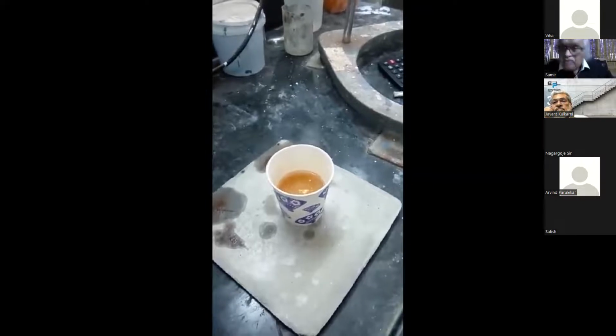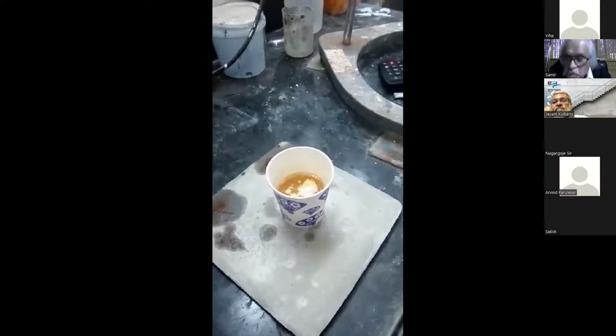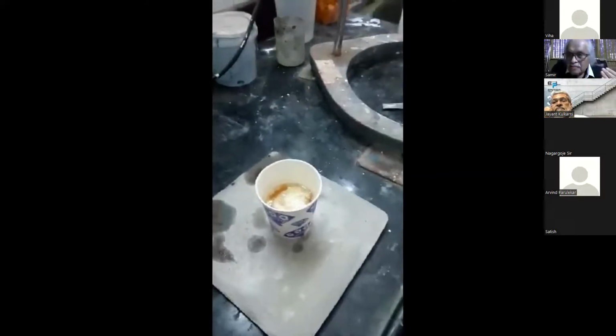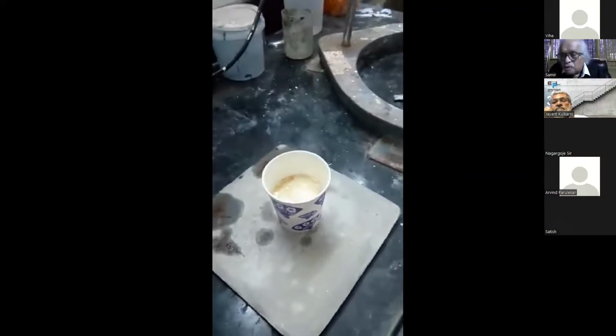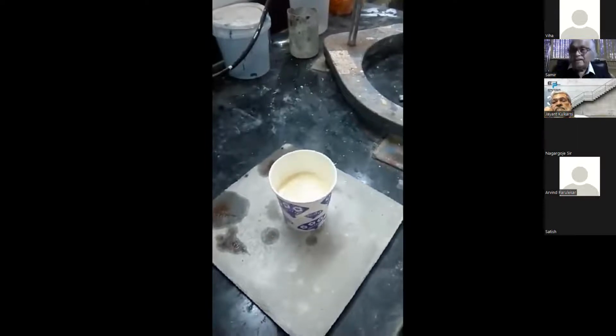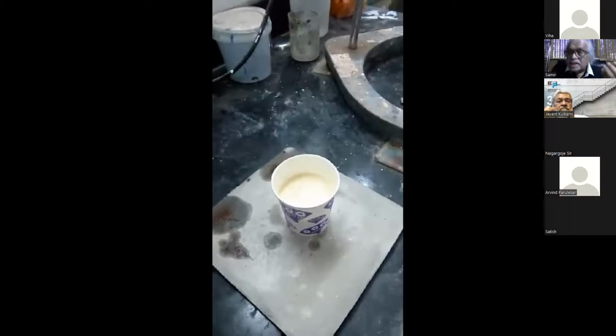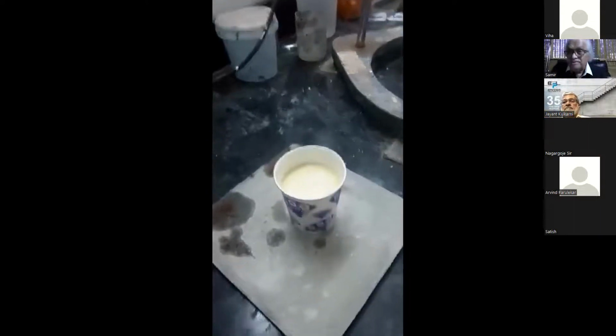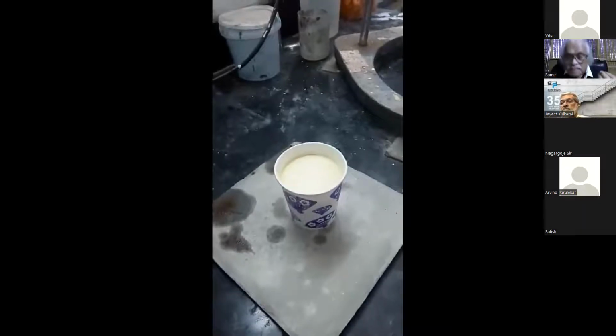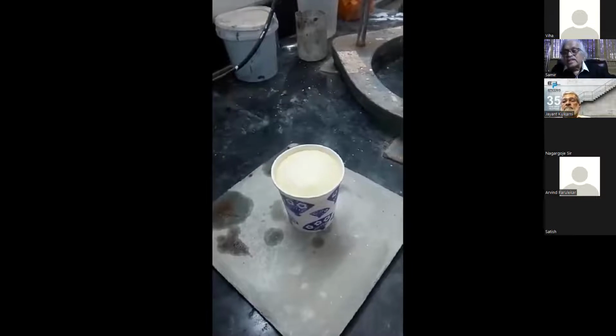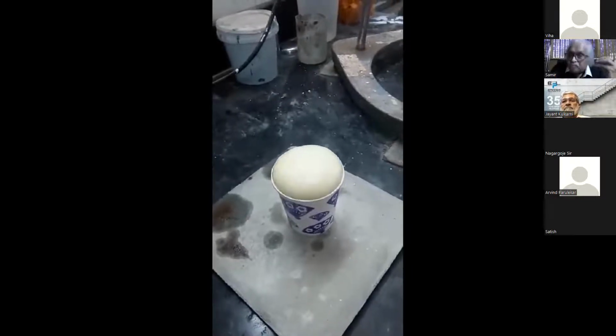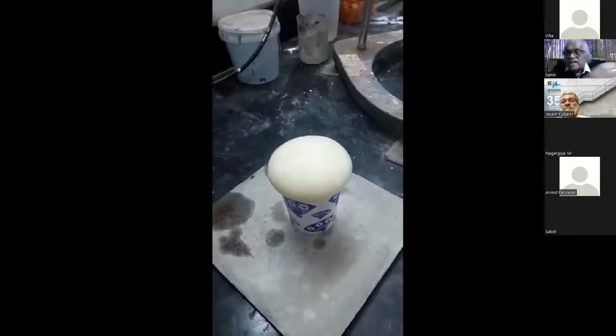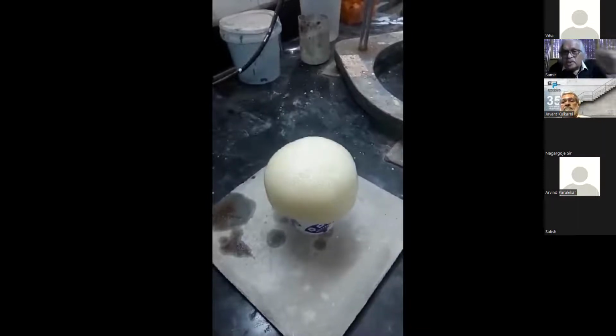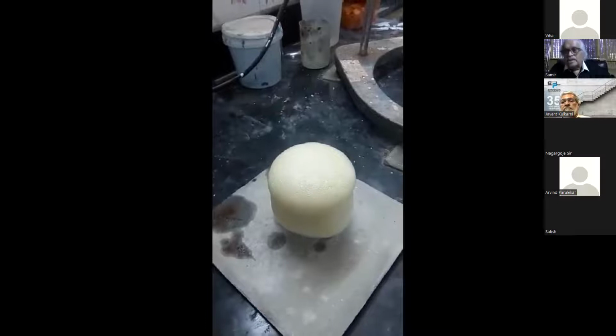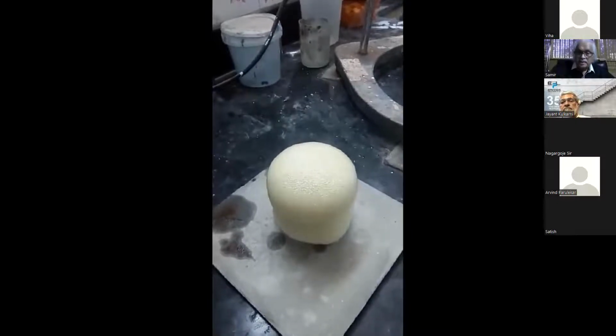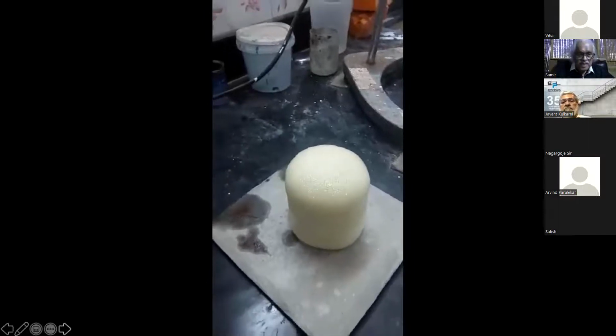And then there is a price. Some person says my foam is only 400 rupees, and his is 900 rupees. It depends on the volume factor. We engineers don't even think about it, because the foam costing 400 rupees has an expansion factor of only 15, and the expansion factor of the foam at 800 to 900 rupees is 75. That means 5 times. For the 900 rupee product you will require only 20 kilos, whereas you require 100 kilos of the 400 material. So please don't get fooled. This has a life of 3 months, and waterproofing and the concrete should have a life of more than 150 years. So these are different types of resins. Please be careful.